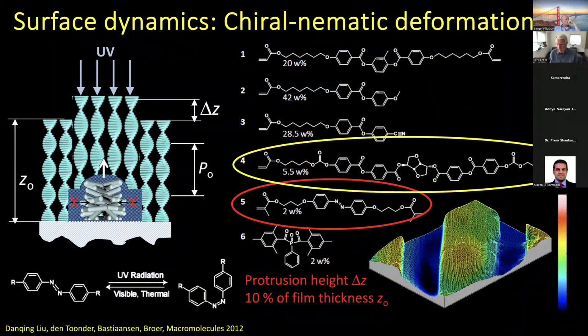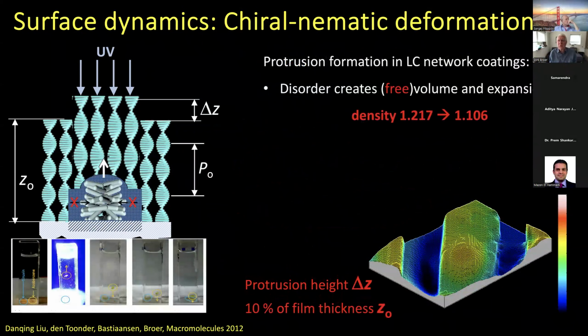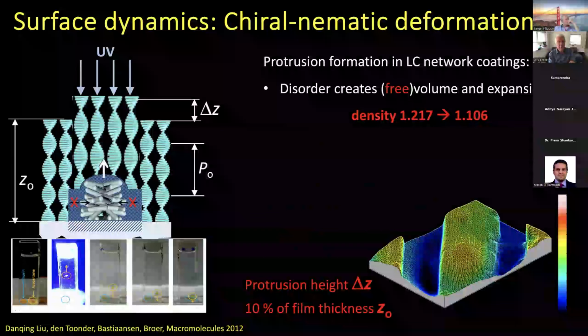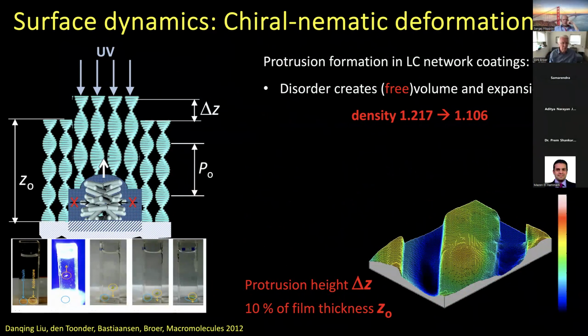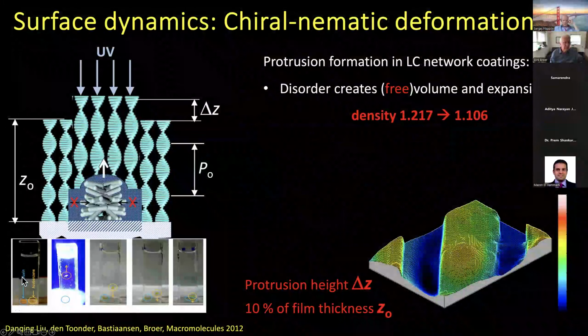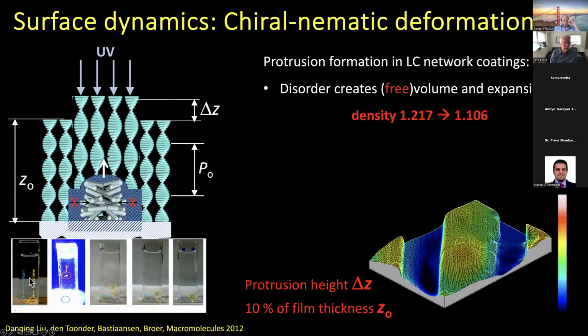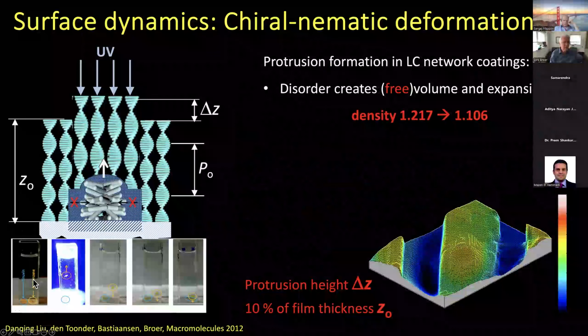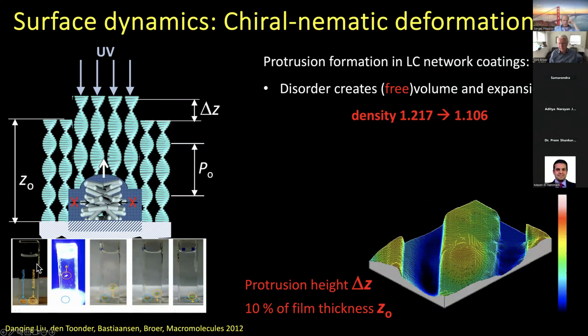So we dove somewhat further into the study. And what we also could find is that the decrease in order also created free volume, and that is shown in the experiment on the left. So here we have the film with azobenzene and a film with Tinuvin. This is the reference sample, which absorbs as much light as azobenzene, but doesn't give the deformation. So then we start exposing it.